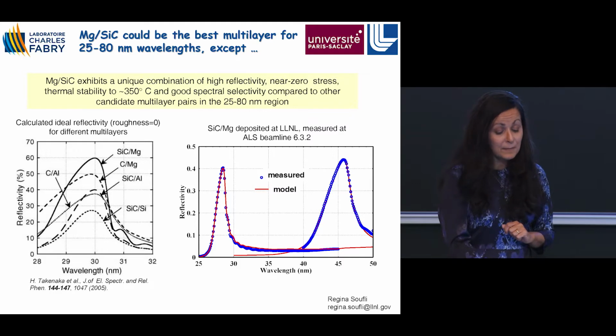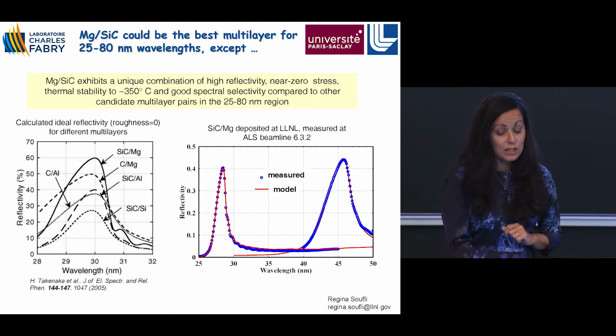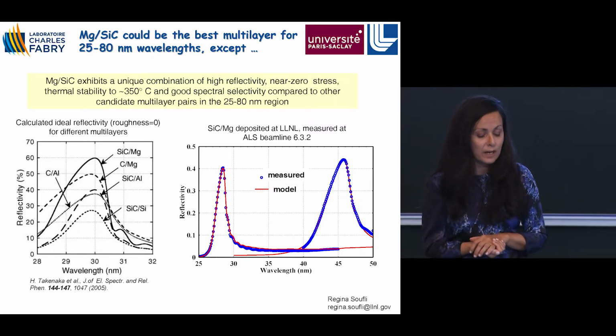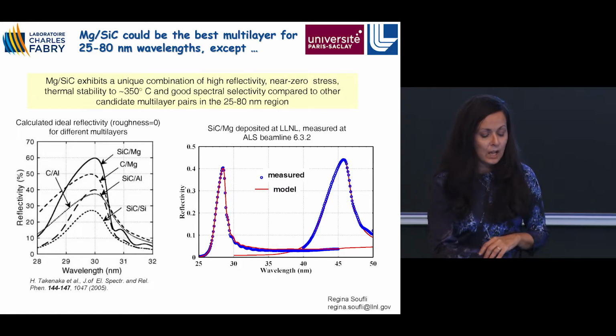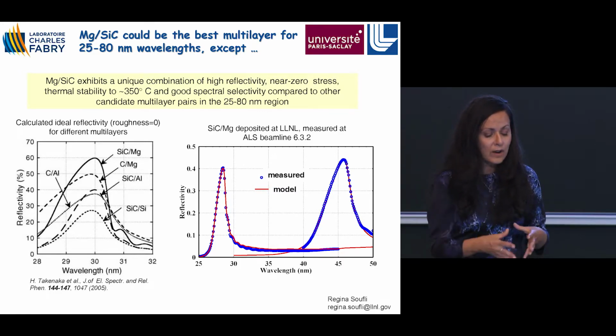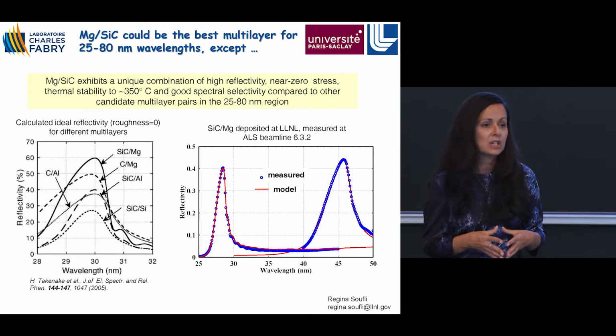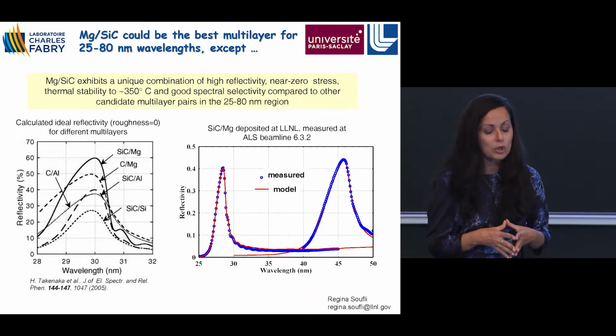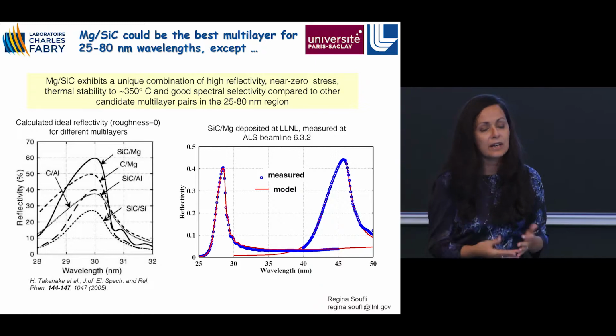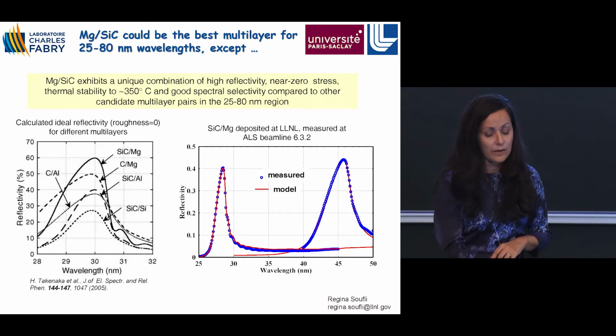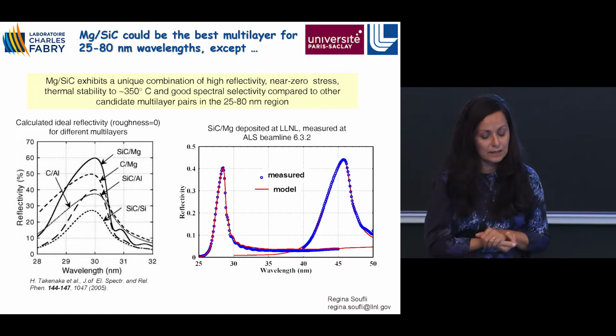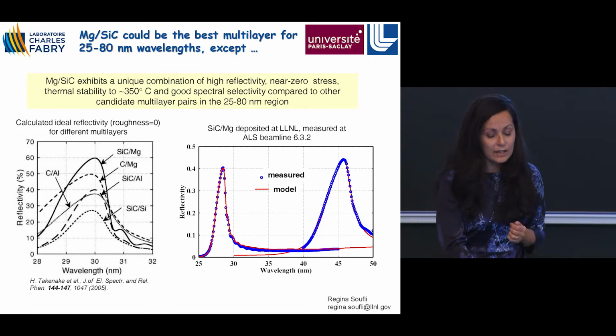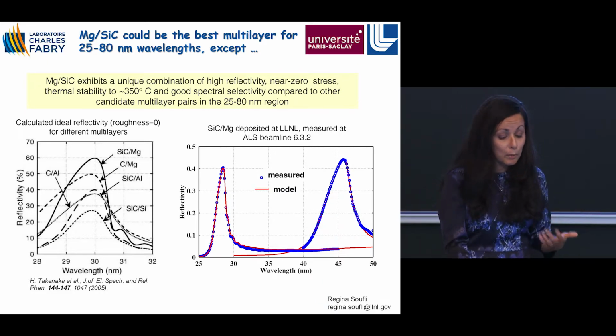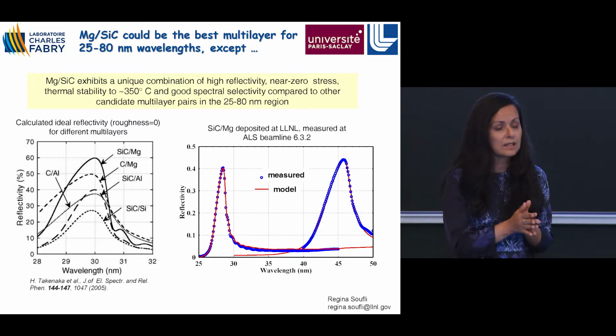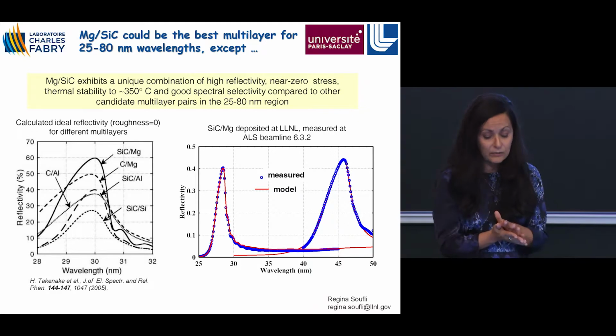And there is a material system, magnesium silicon carbide, that works very well in this region, as you can see here. It is because this region is right below the magnesium L edge, and as I was mentioning, you have a low absorption, and therefore you can achieve high reflectivity in this wavelength range using this material system. In addition to high reflectivity, you have a set of other good properties for this coating. It has near zero thin film stress. This means that the coating is not going to delaminate from the substrate.